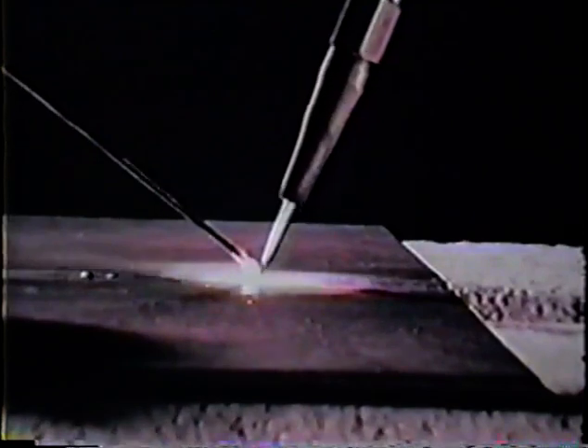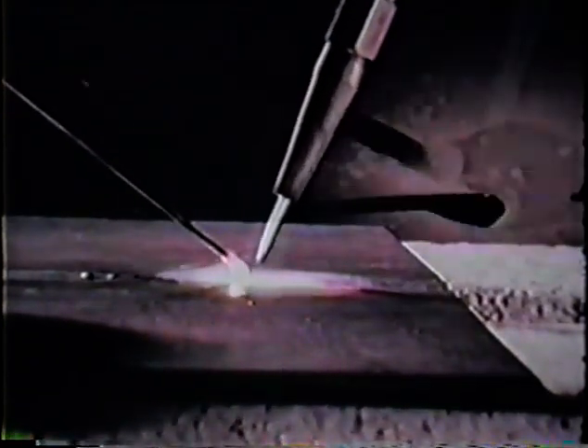The flame should be angled 45 to 60 degrees to the plate and should be pointed toward the direction you intend to weld. Keep the torch moving constantly in a horseshoe or circular motion to push the weldment along in an even pattern. Keep adding rod to the puddle, but do not stir it, because oxides will be imparted deep into the puddle.